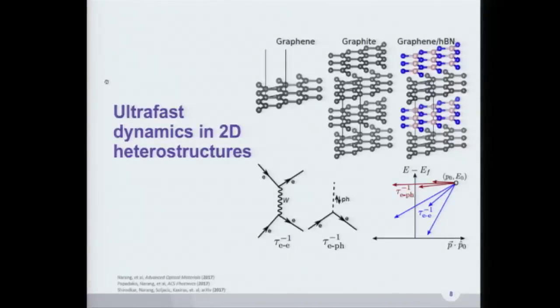And something we realized is that the in-plane lifetimes are actually very strongly dependent on out-of-plane interactions. And this is primarily seen in the electron-phonon time, not the electron-electron time. One way you could think about that visually is that if I have a sheet of a 2D material that's like a carpet flopping in the air, and when I lay it out on a hardwood floor, it's essentially held down. So there's some set of soft phonon modes. We don't have to get into specifics of which phonon modes, but some of them would be more dominant and therefore give us shorter times when you have this floppy sheet rather than when it's laid out on a floor.